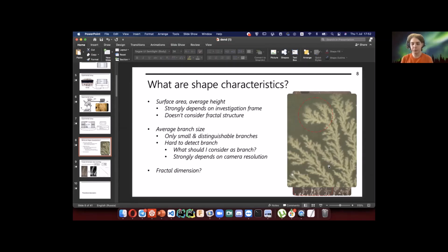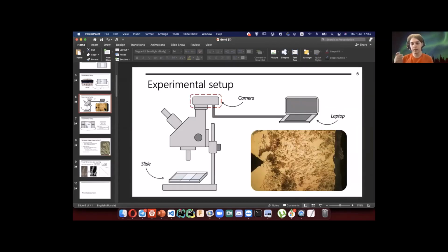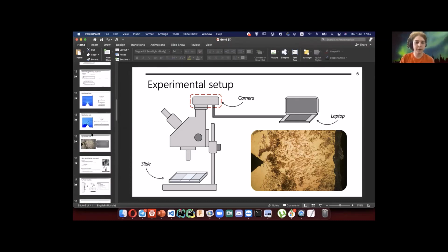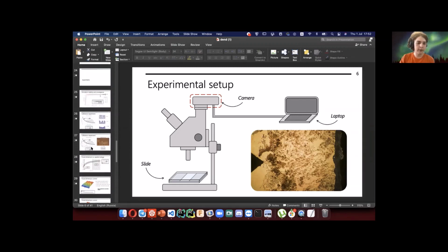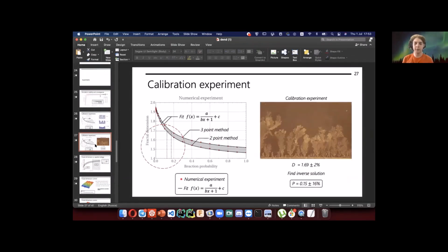About the remarks which were raised during the report overview by the opponent. For example, he said that we didn't investigate the electrode shape. However, you can see that we conducted the experiment with a triangular shape to see that the dendrite starts to grow faster near the sharp edges. And other experiments were conducted on flat pieces of foil. So partially, we considered the effect of electrode shape. So that's all. Thanks to the opponent for the discussion.